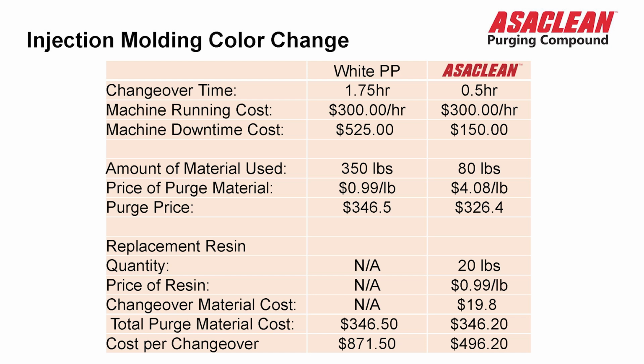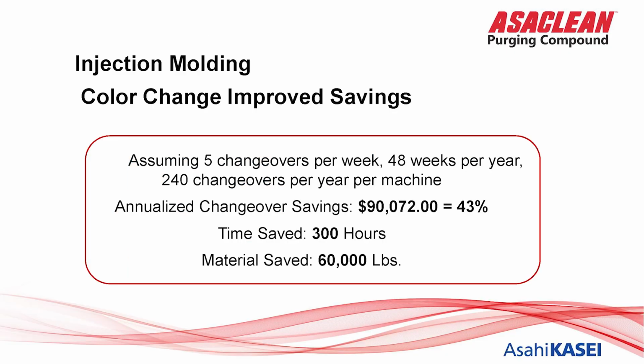We used 350 pounds of material versus 80 pounds of Asaclean. If you take a look at just the bottom line on the cost per changeover, we reduced it from $871 to $496. And after amortizing that out, the cost savings add up dramatically. If we're doing 5 changeovers per week, 48 weeks per year, annual savings is $90,000 or 43%. And we were able to give them back 300 hours of valuable productivity.